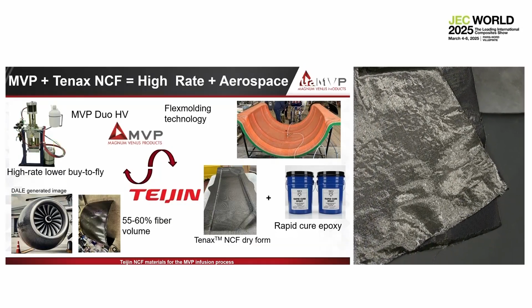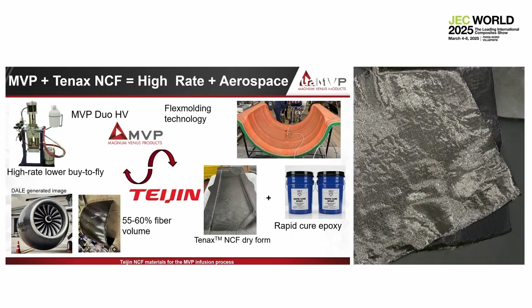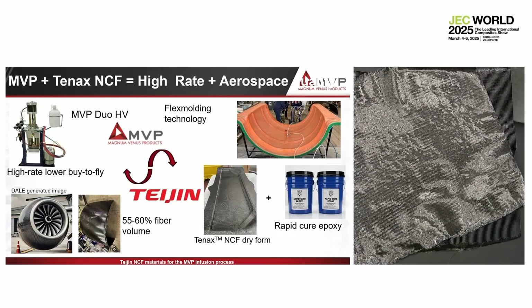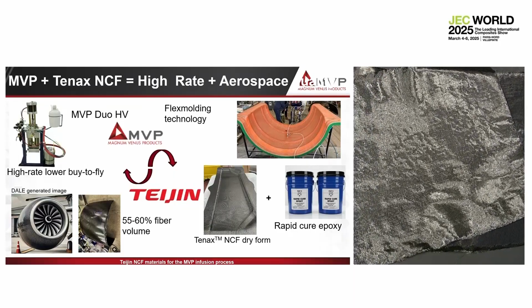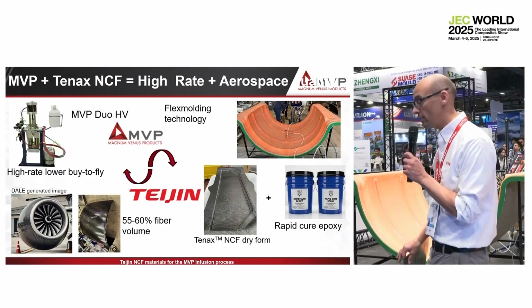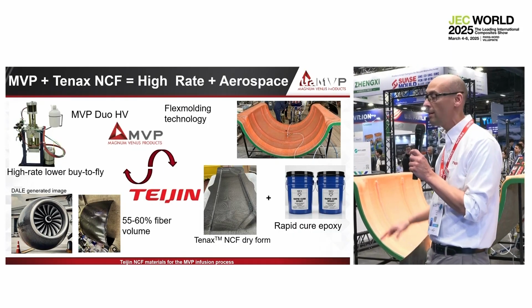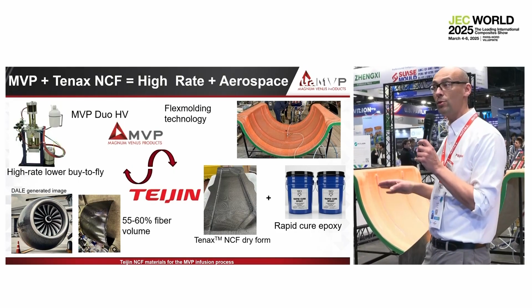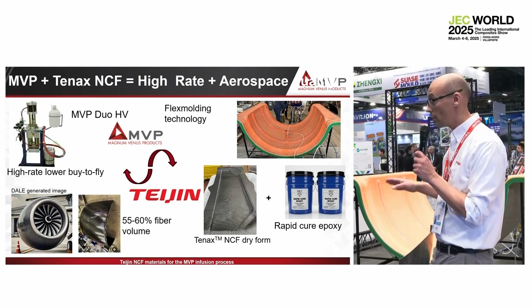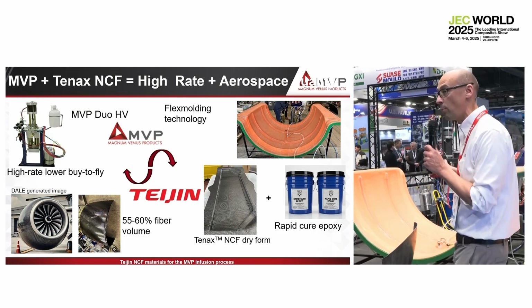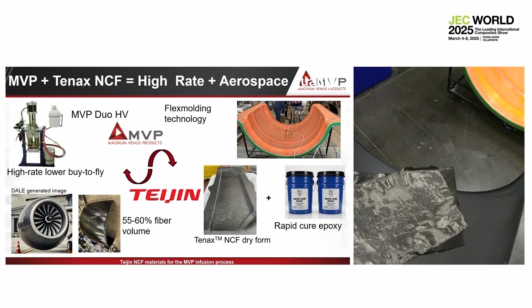The second thing is we're looking for high fiber volume, and that's where the quadraxial comes into play. We get good permeability, good drape, and with a thin skin like this, at high rate, we're looking at 55 to 60% fiber volume with epoxy. This is with polyvinyl ester. You can get that here.